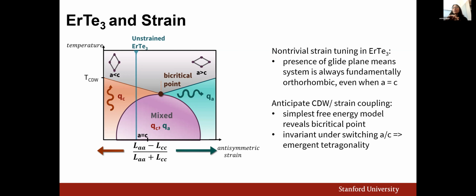It gets a little bit more interesting, though, if we think about how the charge density wave order might couple to strain. So if we admit terms into a free energy expansion that allow for a coupling between CDW order and uniaxial strain, the simplest phase diagram that we can draw is shown on this slide. And what we can see is that indeed we can flip between CDW order along the C axis versus the A axis as we apply uniaxial strain. Most interestingly, this also reveals that there indeed is a bicritical point where the phase transitions between that C axis CDW order and the A axis CDW order coincide.